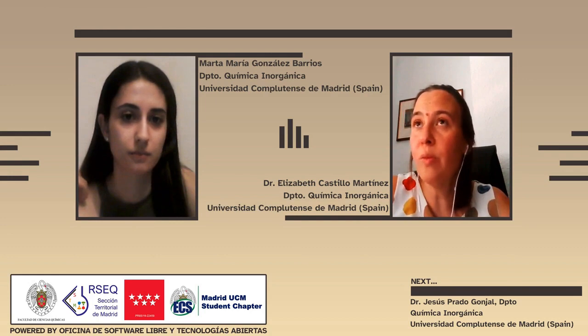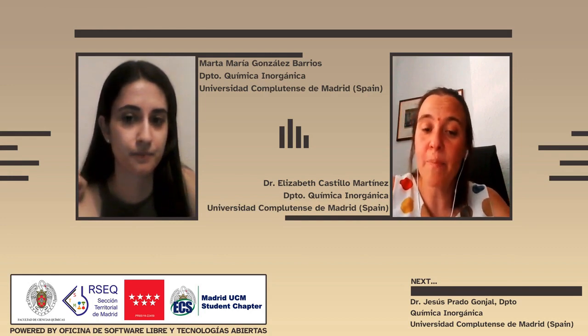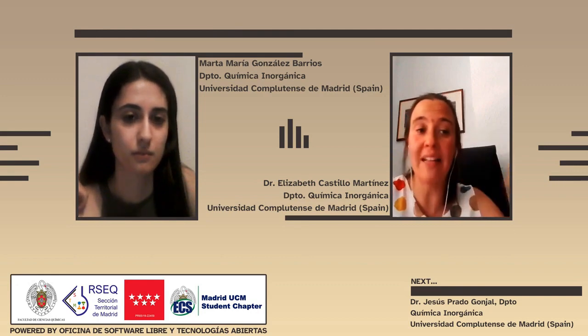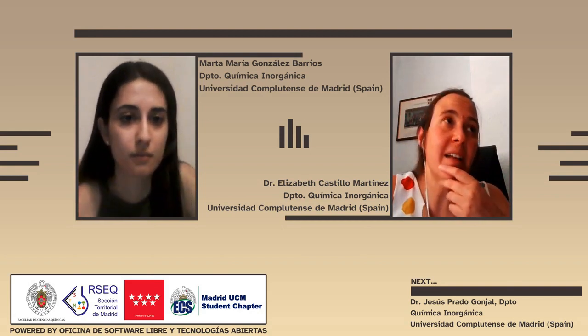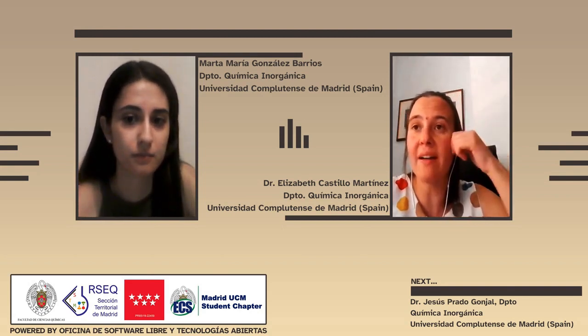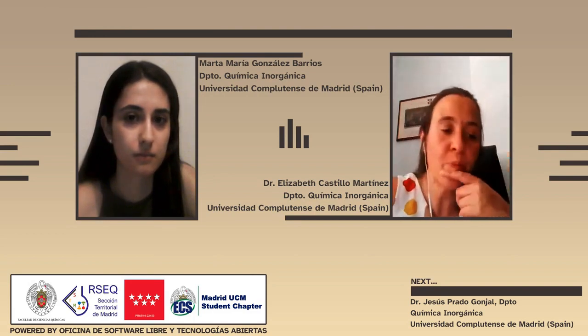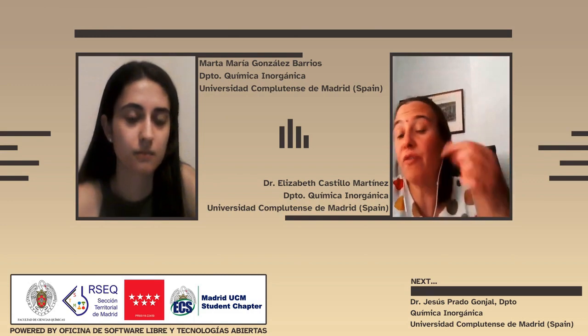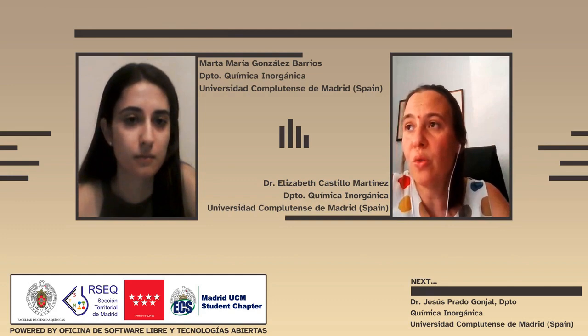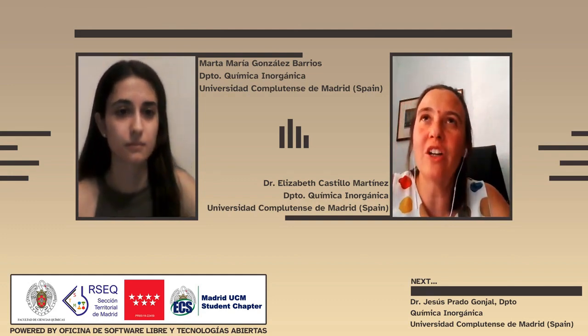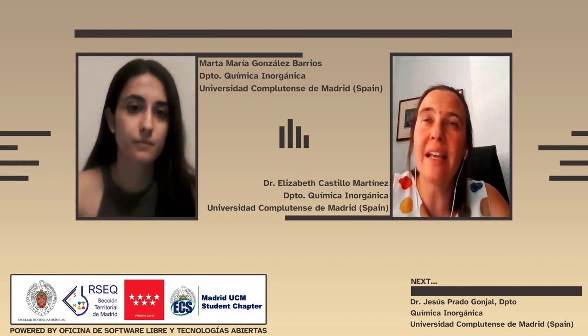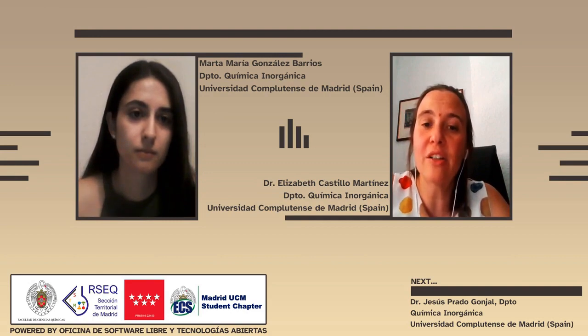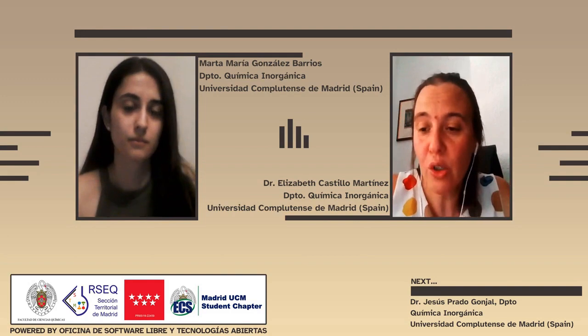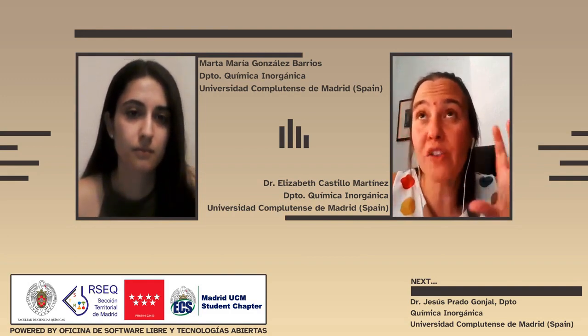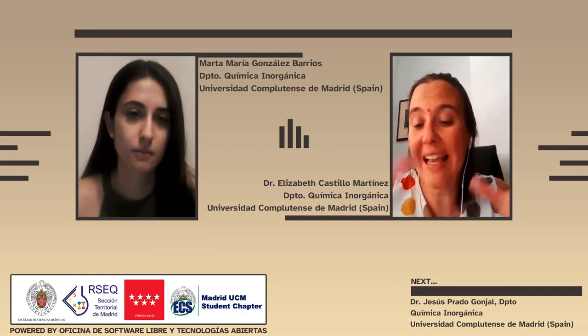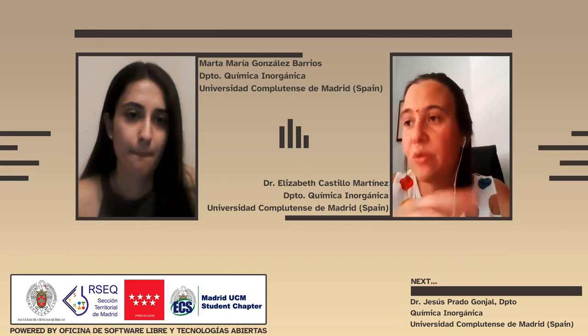So the preferred choice will be to use, as I mentioned at the beginning, a metal electrode material in the middle of a plateau reaction, or just to use an external reference, like maybe a silver or a platinum wire, but careful with platinum as it can promote the decomposition of the electrolyte, so maybe a silver wire and some ferrocene to do it. But this is not very commonly done. I would think once you characterize your material in a 3-electrode cell, it is more common to then try to build a cell completely free of sodium or potassium, a 2-electrode cell against another cathode, if you're studying another material, against another cathode already well established.